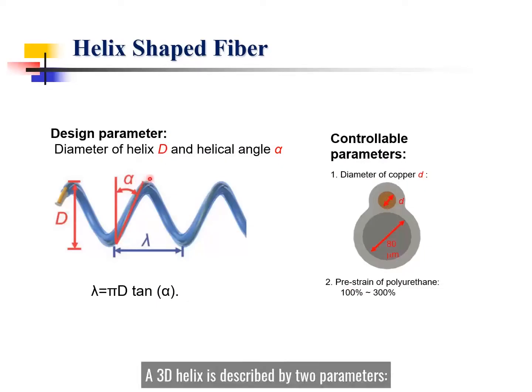A 3D helix is described by two parameters, diameter d and the helical angle alpha. The pitch of the 3D helix lambda is related to these two parameters via this formula. The diameter of the PU fiber is 80 micrometers, whereas that of the copper fibers ranges from 25 to 40 micrometers.